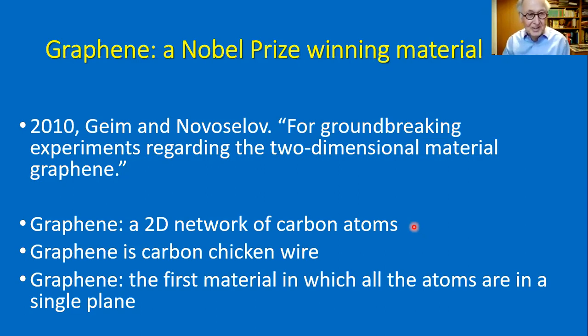So the plane of atoms is just a 2D material. Pi electrons above and below give it some thickness. And the thickness of a single monolayer graphene is about 3.4 angstroms, if I remember correctly, something like that. And you can define the thickness. I shall just say this: if you have a block of graphite and you measure its thickness, and then you count the graphene layers in the block using electron microscopy, say, and let's say you've got 100 layers, and the block of graphite is 340 angstroms thick, then each layer is 3.4 angstroms thick. So that's one way of measuring the thickness of graphene.